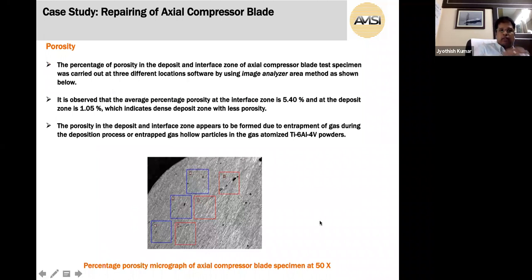Later on, we also studied the porosity. Porosity is a very critical factor of any engine components when we deposit using any additive manufacturing process, such as blown powder, or it could be a powder bed fusion. The porosity contributes a lot in terms of controlling the strength of the component, and we should have minimum porosity to have a better structure, better bonding and better strength of the component.